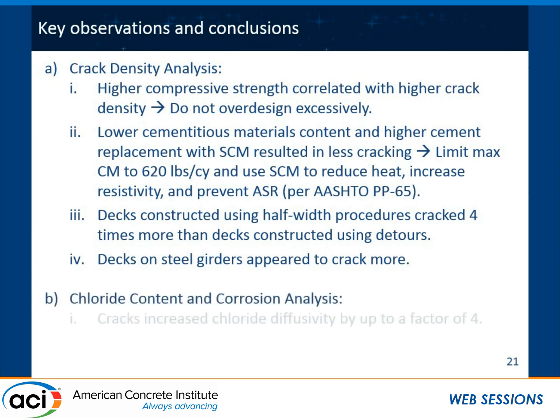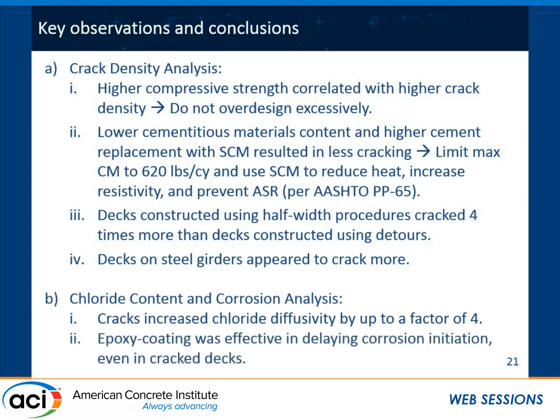And in chloride content and analysis, cracks increase the diffusivity by up to a factor of 4. That makes sense. And also epoxy coating was effective in delaying corrosion initiation, not permanently, of course, but even in the case of cracks. Thank you very much.